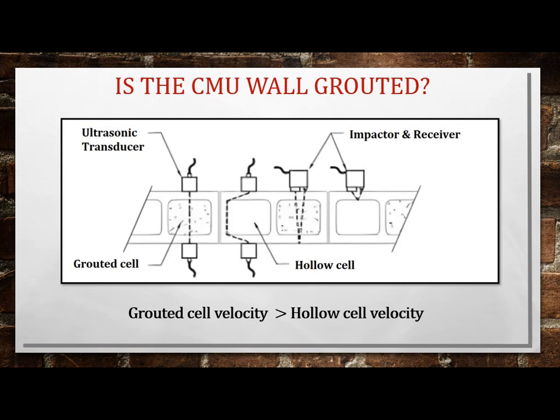And here's another one: is this CMU wall grouted? This is where you would actually send a sound wave, and we've done this a few times. You have to have a real long coaxial cable, because one guy has to be on the outside of the wall, so you can shoot the sound wave across. A grouted cell is going to have a faster velocity, a shorter transit time. With an ungrouted cell, the sound has to travel around, so it's going to be longer.